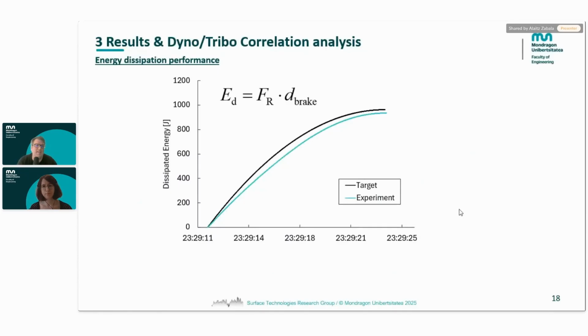Again, on the x-axis we have the time, and on the y-axis we have the dissipated energy evolution. Here we can see that there are some discrepancies between the experiment and the target. This is because, as I said earlier, the friction force is not constant during braking. At the start we have a little more difference, but at the end we correct that and obtain quite close dissipated energy. So this is for one brake event.